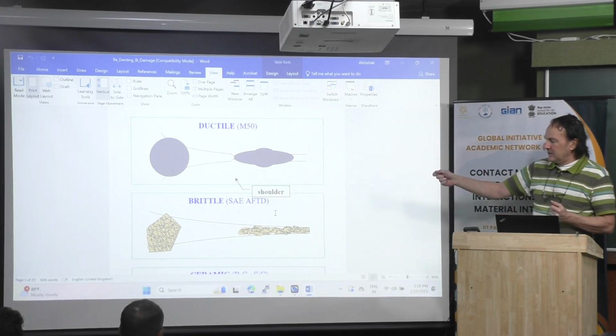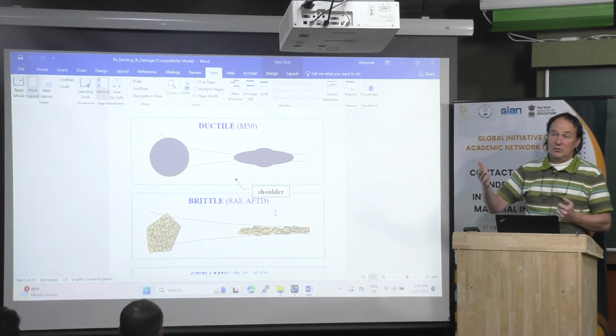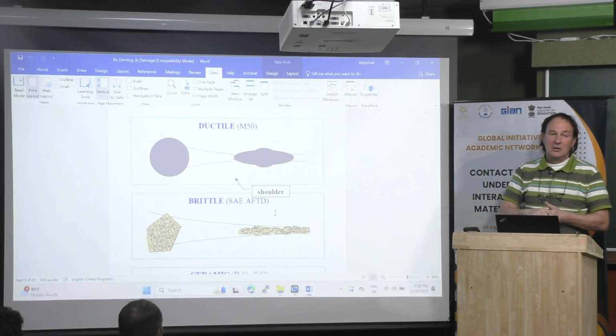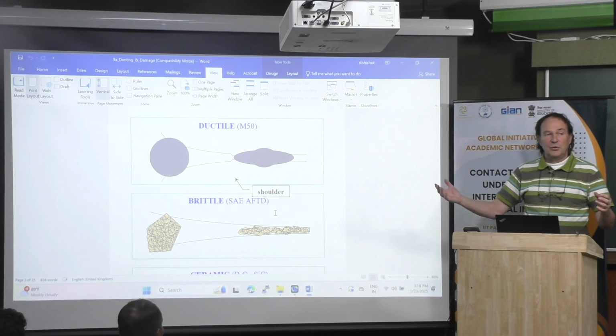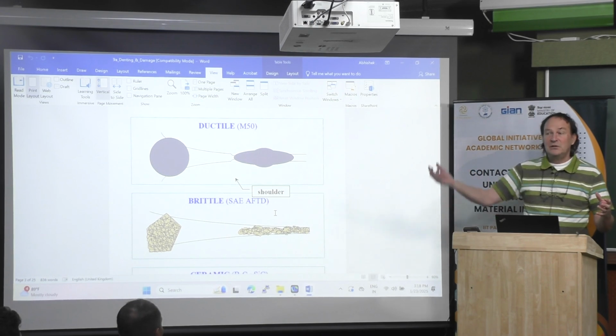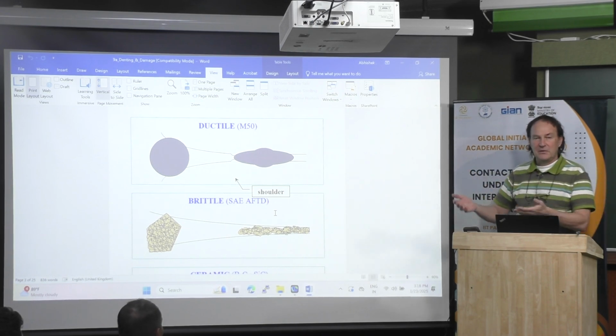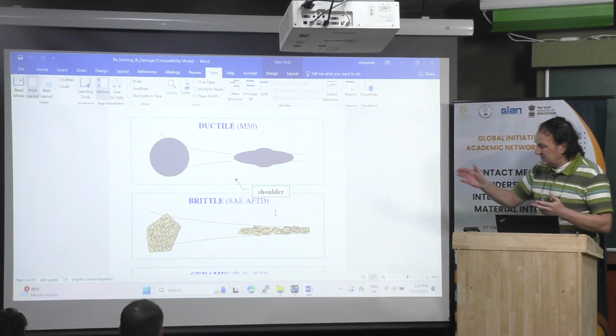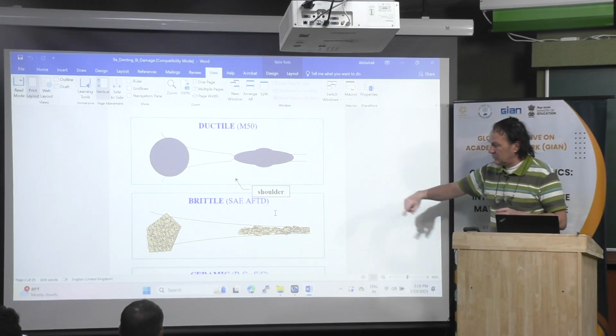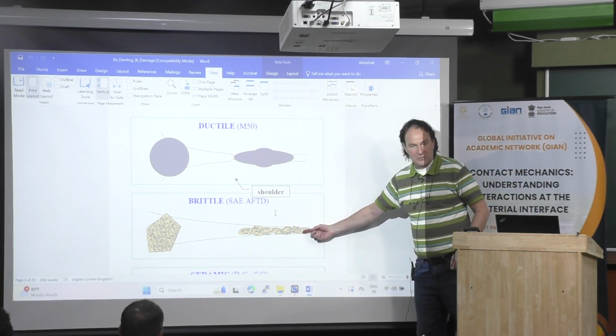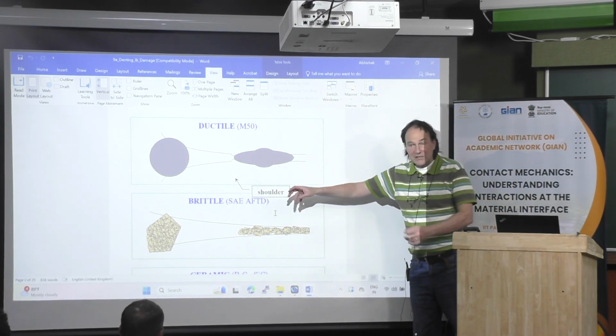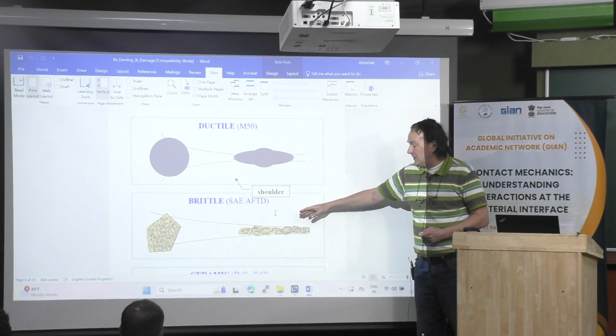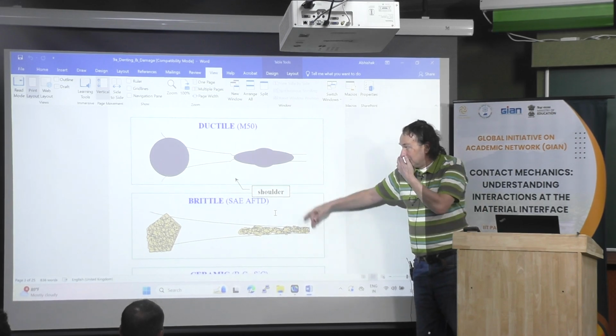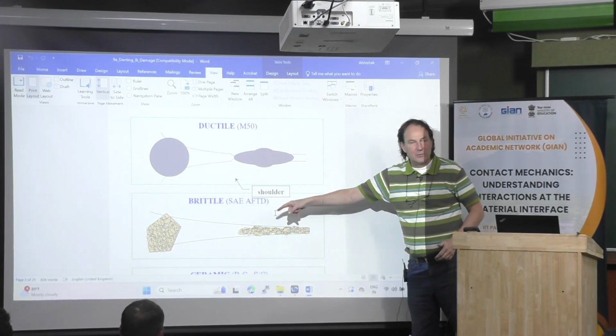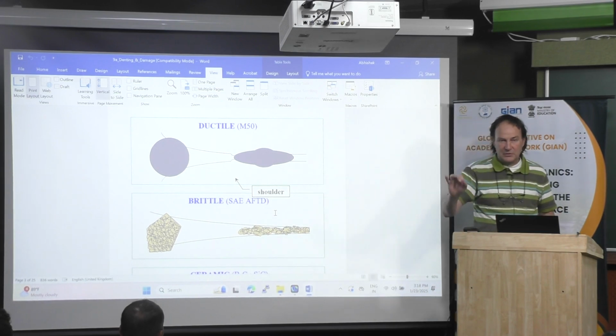And this typical sand is used to make a test on many devices. For example, for helicopter engines, they use that for ingestion of sand into the engine, and this is a standard method. Okay. But this is not the main purpose. It's here just to see that when you have a brittle material, it will break in many small parts, and you can observe on the surface not only one dent but many dents each time a particle of sand enters into the contact.